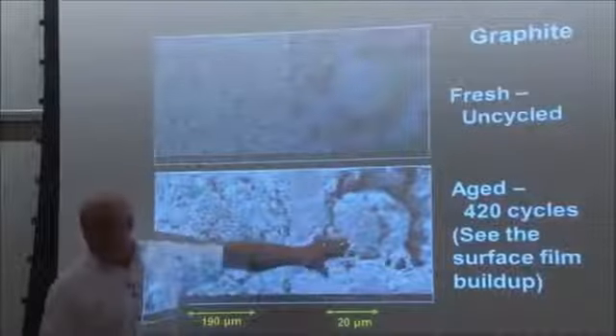Last quick question. Based on your model, you mostly focus on the surface of your negative electrode. So the SEI forms on the surface only, or does anything happen inside the pores, I mean the graphite inside the pores? That stuff is not what I would call SEI. This is the reduced oxidation products coming from the other side. It's junk, and you can see it with an SEM. The normal SEI is just a few nanometers thick, and you can't see it on an SEM at this scale. So this is junk that's come from the positive and been reduced on the negative surface.